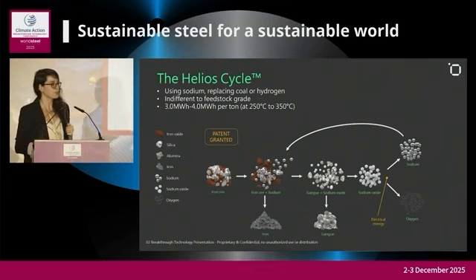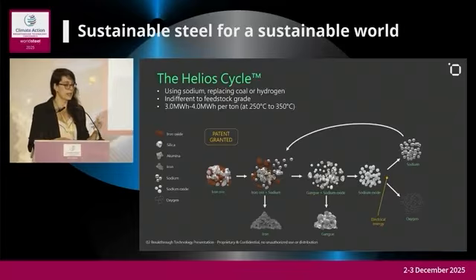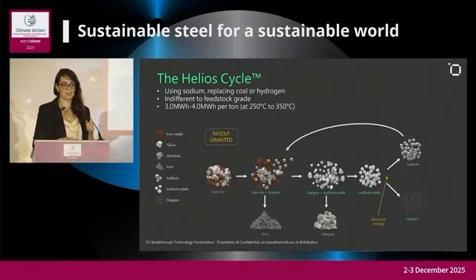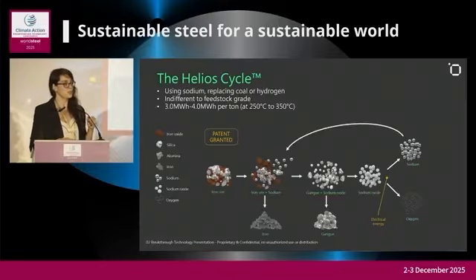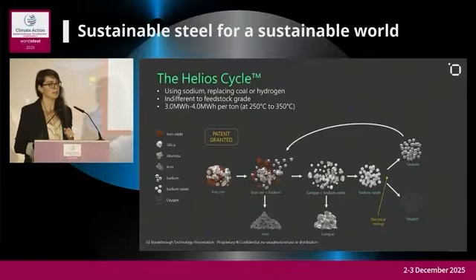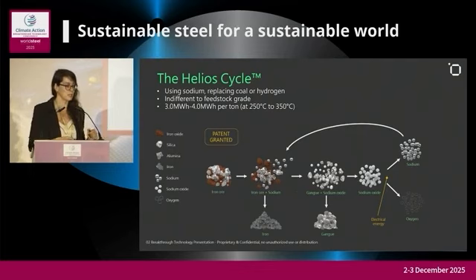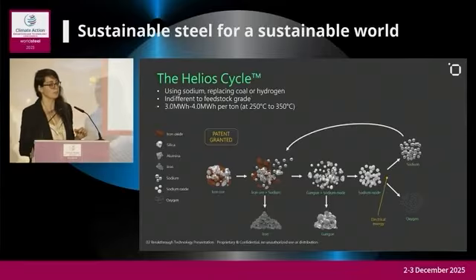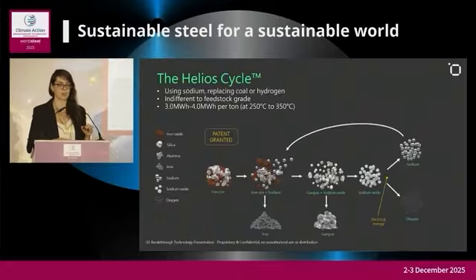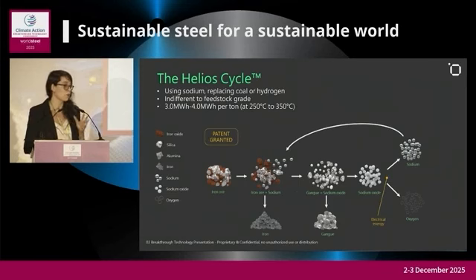Why are we indifferent to the type of feedstock? It means we can use low-grade iron ore and even waste products such as tailings and slag, and we will talk about it in the next few slides. It's because sodium is thermodynamically selective to the reduction of the iron oxide, meaning it reduces only the iron oxide and does not touch other components in the material. The energy consumption is 3 megawatt hours to 4 megawatt hours per ton, and the operational temperature is between 250 degrees Celsius and 350 degrees Celsius. This is critical because we can implement it in the infrastructure of the industry without any significant or extreme retrofitting.